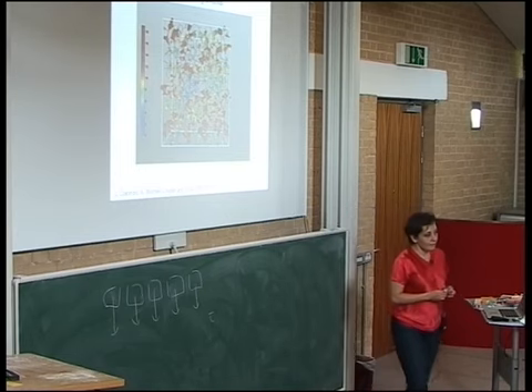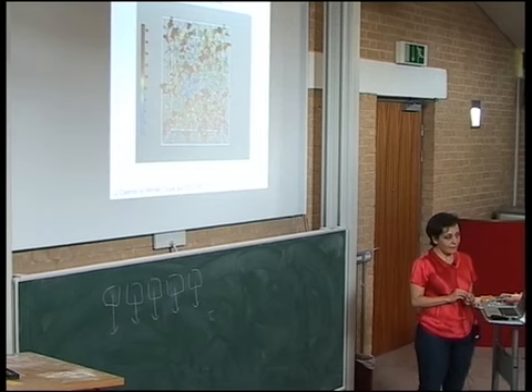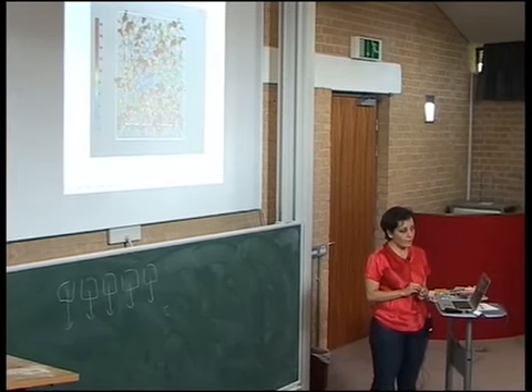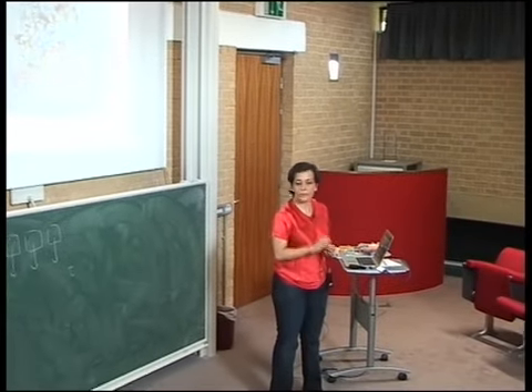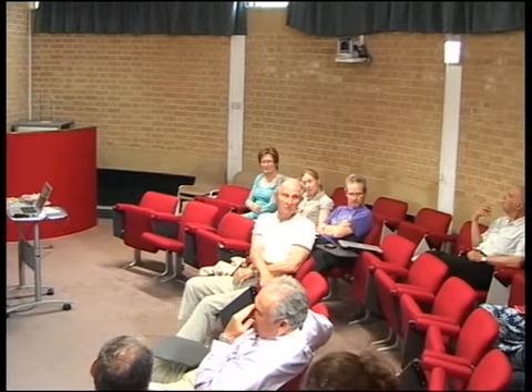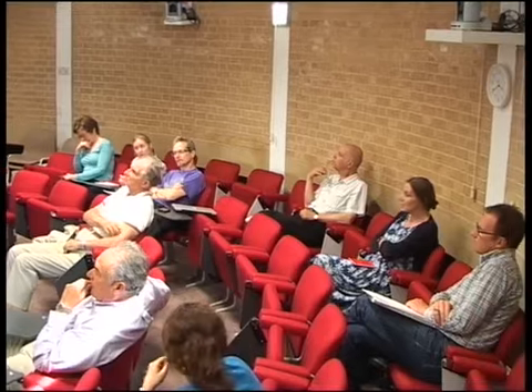Sorry, is that the number of breaking events per bond, or the number? I'm worried that things don't break more there because there are more bonds there to start with. It's per bond. So is it that things break more in the red regions because there are more bonds there to start with? No. So they're more likely to break. It is independent from the number of bonds that are there. It's a breaking probability per bond.